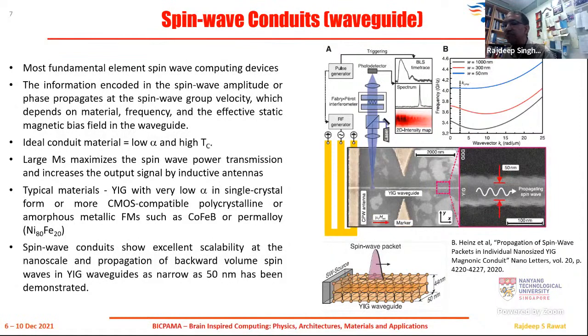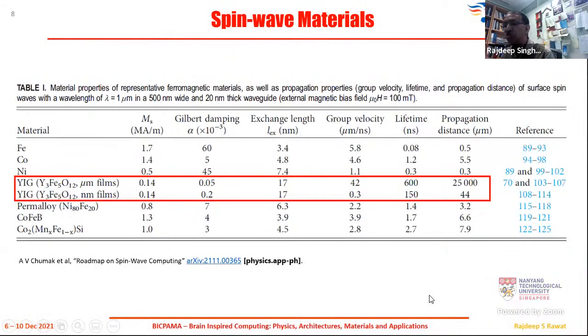Now, as we all know, for CMOS technology, the basic computing element is a transistor, whereas for a spin wave, it is the spin wave guide, the conduit. One of the requirements for this spin wave conduit material is that it should have low alpha, that means a low damping factor, because if the wave propagates in it, it should not damp by itself, which would lead to a change in the amplitude. And if you have amplitude-based encoding, then the state will change. So you don't want that. So they need to have a low alpha, as well as a high Curie temperature and higher magnetization. For that purpose, YIG happens to be an excellent material.